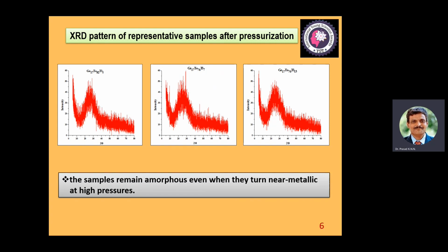So what we can notice here is that the samples still remain amorphous even when they turn near metallic at high pressure. See, what actually used to happen was, chalcogenide glass is basically a semiconductor in nature, and when you apply a very high pressure of the order of say 3 to 10 gigapascals, there is usually a transition occurring from semiconductor to near metallic.